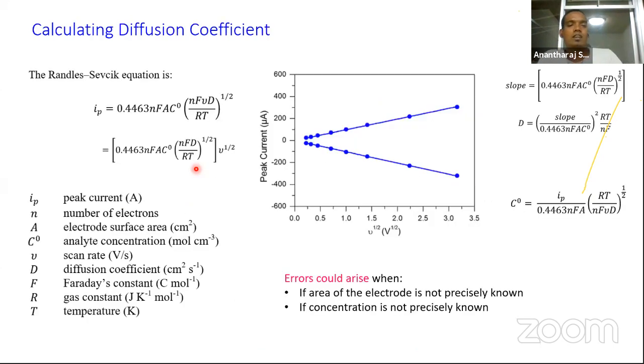Next is the diffusion coefficient, which is very important when we are interested in promoting a particular redox reaction for industrial level production of a particular product. The diffusion coefficient of a species in solution must be known. Other than that, for studying the reaction kinetics, the diffusion coefficient is also important. I told that when the reaction is diffusion controlled, completely reversible and occurring via freely diffusing electroactive species, we can obtain a linear plot by plotting the peak current against the square root of scan rate, such as the one I have given here. You can see a linear relationship, the slope of which is equal to this expression. Just by rearranging this equation, you can get the diffusion coefficients, for the oxidized species as well as for the reduced species.